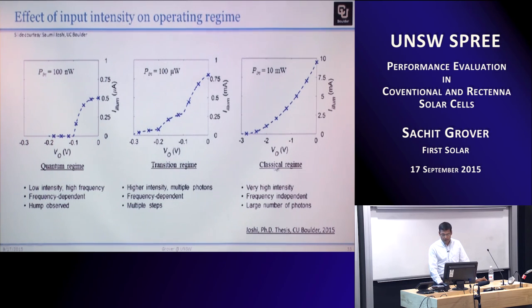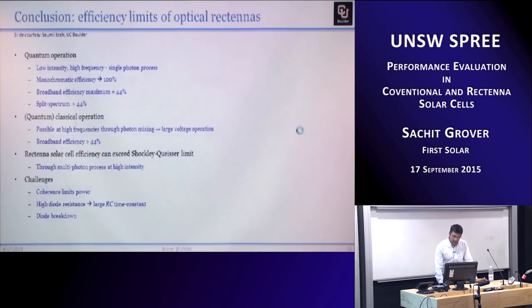And as you increase the intensity further, you get into a very high intensity regime. This kind of curve extends further out, and it smoothens out. So even with tenth of an eV photons with very high intensity, given here as 10 milliwatts, you're able to get up to 3 volts in this curve. So we've broken away from the quantum regime, which limited the voltage to be governed by the photon energy rather than the intensity. So with this, we come to the conclusion for this section, and thanks again to Sawmill for sharing his slides with me.